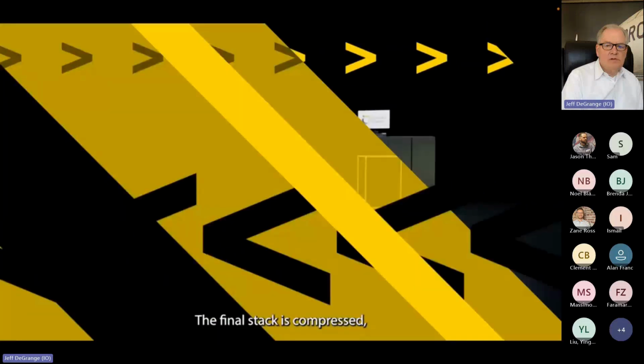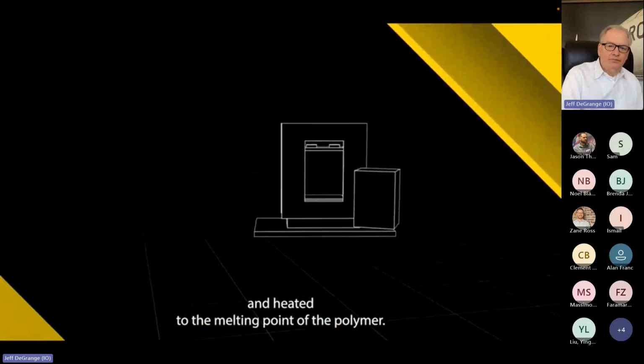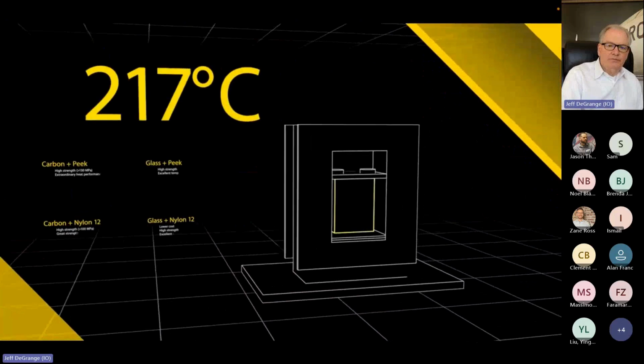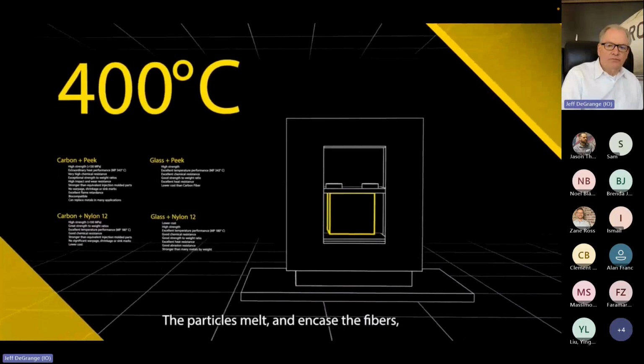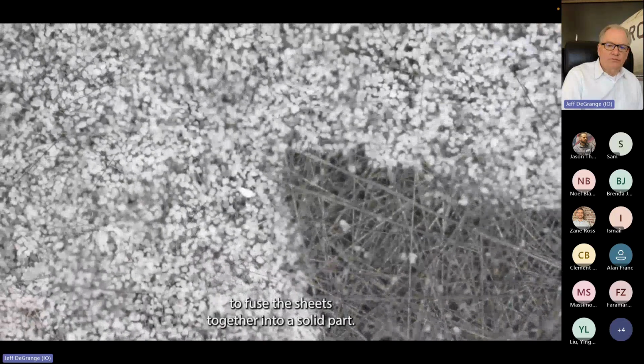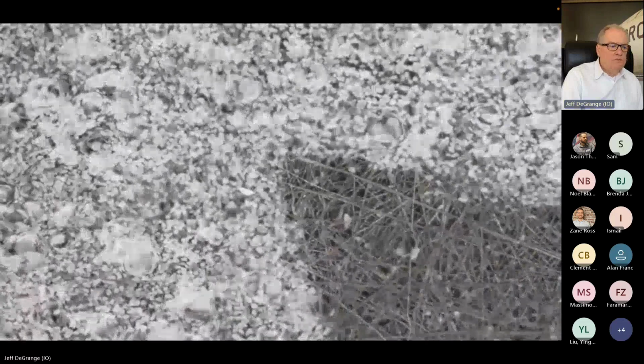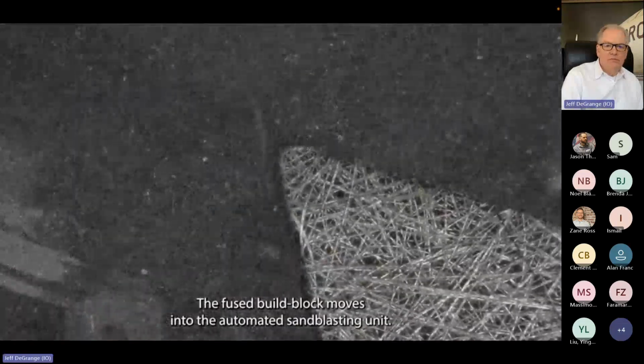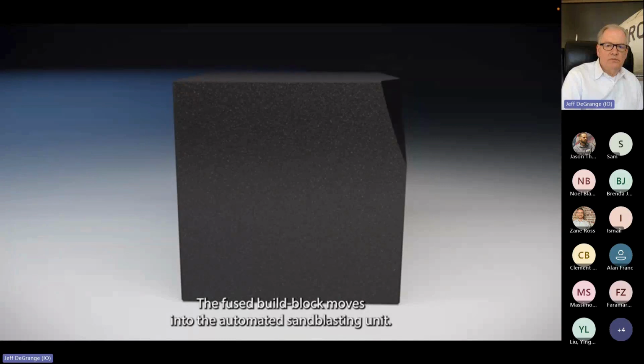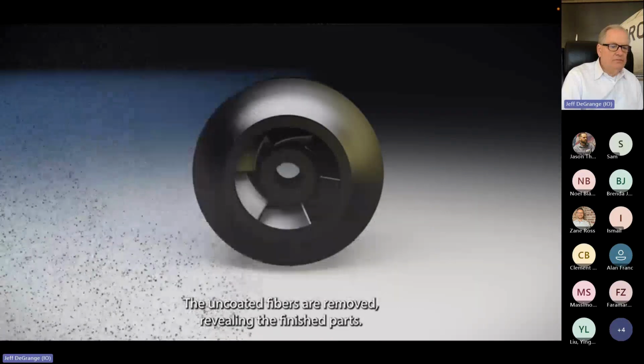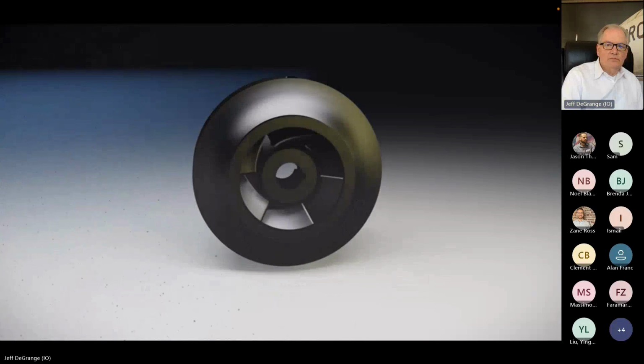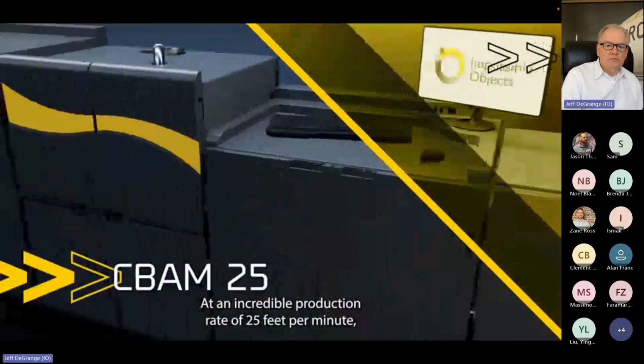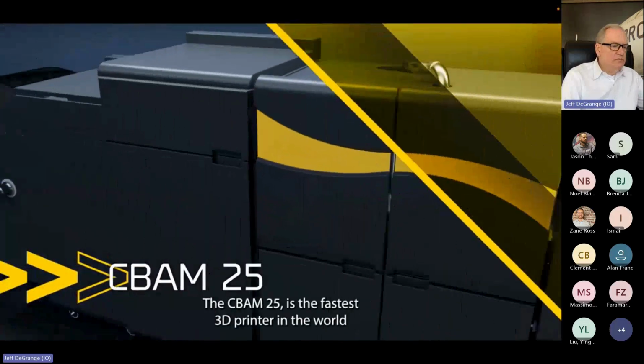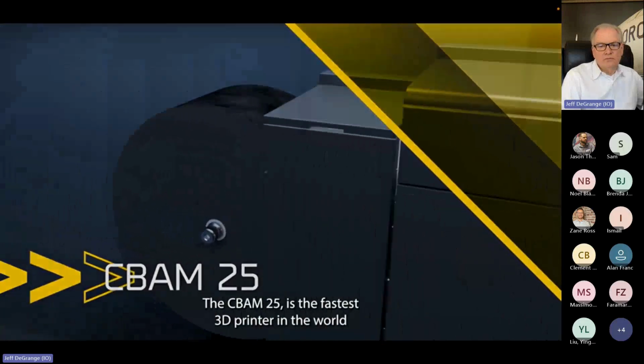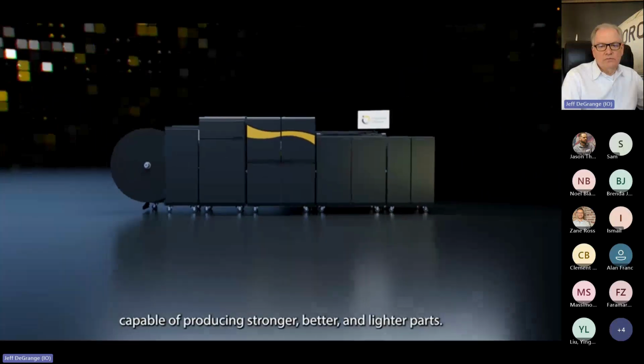The final stack is compressed and heated to the melting point of the polymer. The particles melt and encase the fibers to fuse the sheets together into a solid part. The fused build block moves into the automated sandblasting unit. The uncoated fibers are removed, revealing the finished parts. At an incredible production rate of 25 feet per minute, the CBAM 25 is the fastest 3D printer in the world, capable of producing stronger, better, and lighter parts.